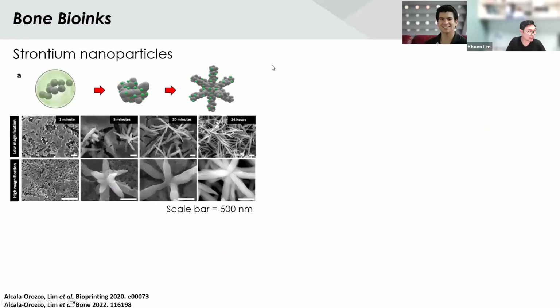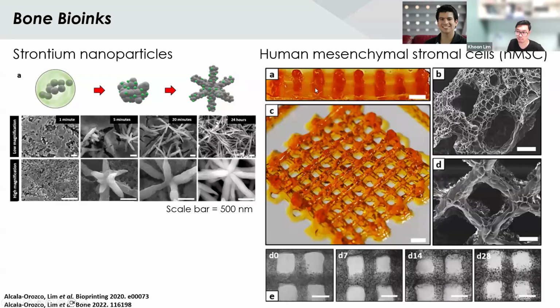When we then look into making bone bioinks, Caesar here started looking into making strontium nanoparticles. So strontium ranelate, for example, has already been used in the clinic. It is being used to treat osteoporosis. So we use strontium as our way to make these nanorods. We again mix them into our gelatin-based bioinks. This time we put human mesenchymal stromal cells within them as we extrude. So you can see that the inks can extrude, you can stack them.